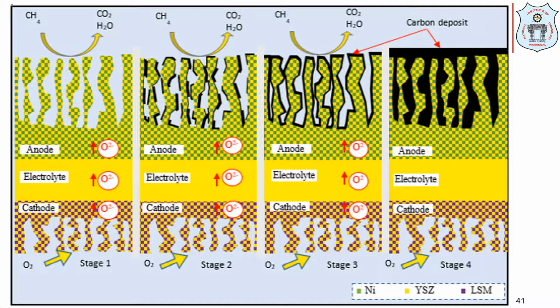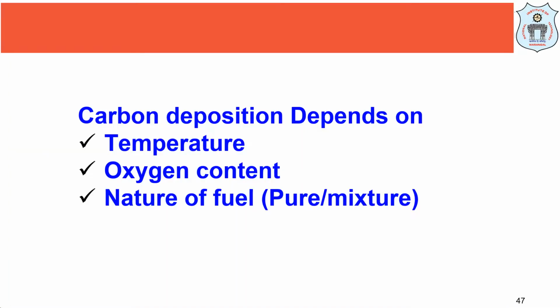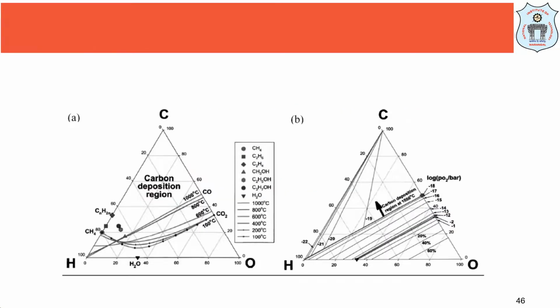Some equilibrium studies of carbon, hydrogen and oxygen content in the fuel, and their relation to carbon formation, have been explained. It is observed that carbon formation will occur at equilibrium depending upon the temperature and the oxygen content. Fuel gas containing hydrocarbon only, like pure methane, is located in the carbon deposition region at any given temperature. To avoid being in this carbon deposition region, the operating temperature should be raised to shrink the region, as shown in the figure. Or we can add an oxygen source such as steam into the fuel mixture, which will bring the fuel mixture out of the carbon deposition region. Nonetheless, the equilibrium study only relates the tendency of forming carbon deposition in the fuel mixture without the involvement of a catalyst, such as in the case of a solid oxide fuel cell anode.